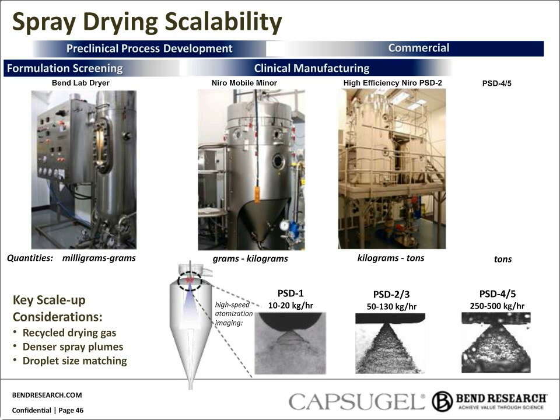So this recycled solvent vapor must be taken into account, since it will contain a significant amount of vapor that will impact the thermodynamics and the drying rate. So in order to predict this effect and account for it early in development, we often operate our smaller scale spray dryers in closed loop mode to mimic the larger scale spray dryers. And we'll talk about the effect of condenser temperature on the thermodynamic operating space in the next couple of slides.